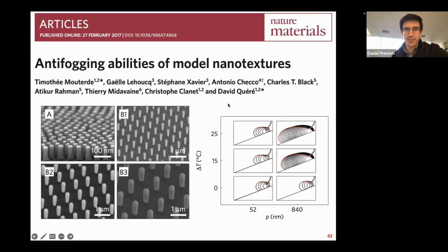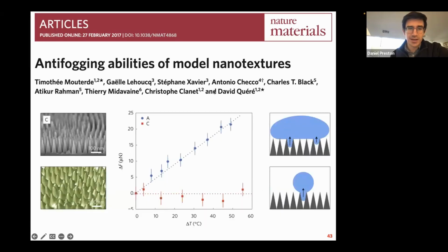So here are some of the samples that they fabricated, and these push down to the nano scale. So we have some pillars that move down to tens of nanometers in size, fabricated in the clean room. They, of course, also looked at different shapes and found that these nano cones are quite effective. But I think a big takeaway here is that I love the work in the sense that it gives us a very satisfying theoretical explanation and an approach to overcome this hot water problem for the superhydrophobic surface, but it still is fabricated in the clean room.